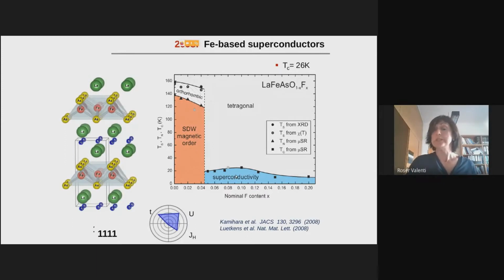And the superconductivity is also rather large. The highest TC in the bulk systems is right now 55 Kelvin. It's not as surprising as for the high TC cuprates, but it's really high compared to what you expect for what we call a classical superconductor. So classical superconductors are those that are described through electron-phonon coupling, and there the TCs are much lower than this 55. Again, here, what we observe is that there is a magnetic phase near a superconducting phase. So again, we have this competition of magnetism and superconductivity.